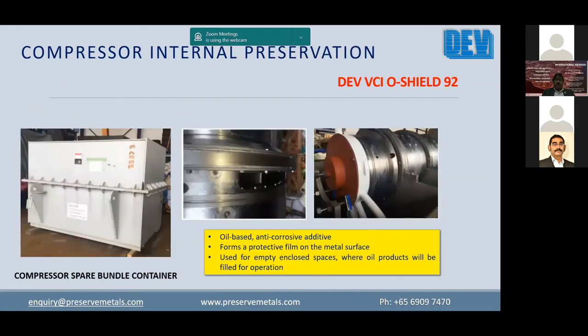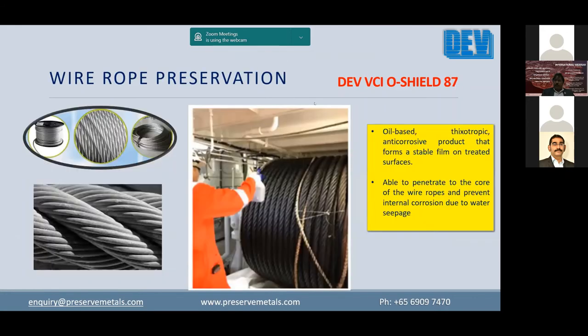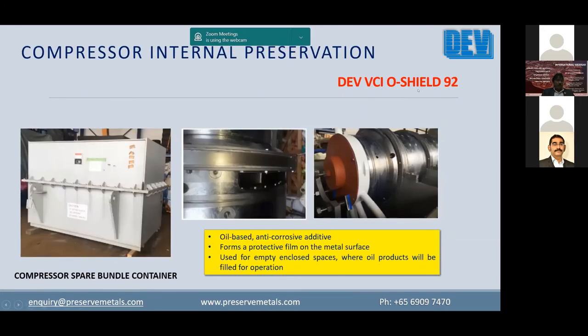Similarly, when it comes to the compressors or the main engines, or other tanks containing oils, whether it's a lube oil or a hydraulic oil, for those types of internal preservation when the system is empty, traditionally it's a problem, because many of these oil-based systems will not have internal paint coating, because this paint, when it peels off, can choke the filters. And such unprotected ones tend to have corrosion problems inside. So there we have one solution called DEV VCI O-Shield 92.